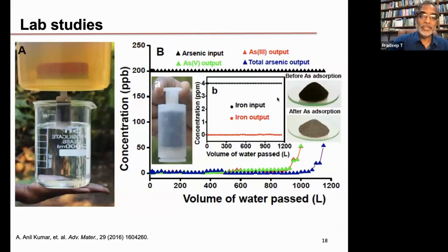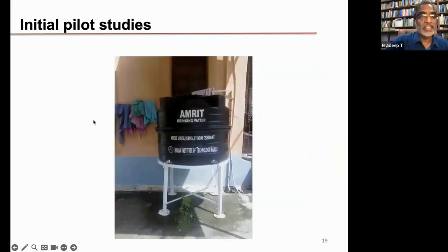So when you do that, you can take this material on a cartridge, and you have 200 parts per billion of arsenate and arsenite combined, 100 plus 100. You choose 100 plus 100 because this is what is commonly there in India. You do test it out all the way up to 5,000 parts per billion to see the suitability of the material across the world. But what is important is that this completely gets removed. And this quantity, about 12 to 18 grams of this, removes this arsenic all the way up to 1,200 liters of water. So you can develop a filter of this kind. And this was then tested in the field.